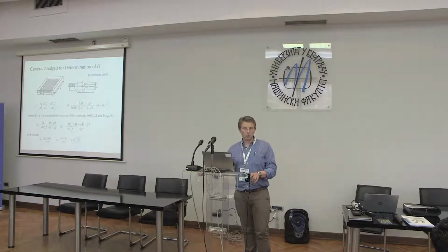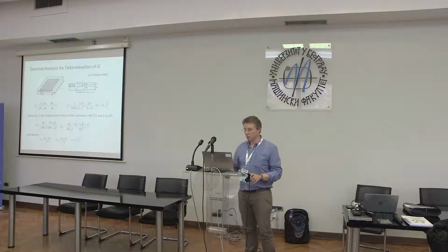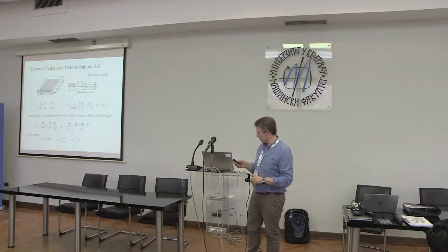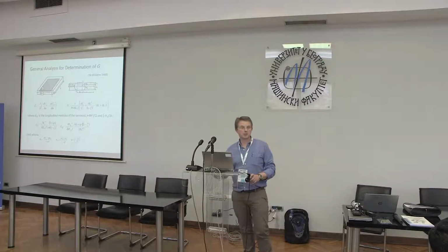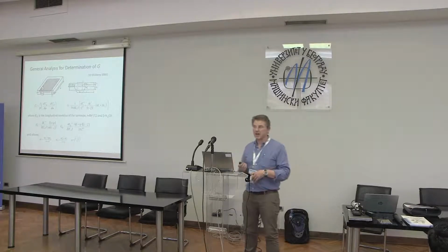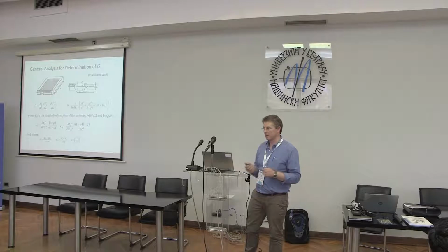Okay, so the important thing of this analysis is that it was a global analysis and worked on the basis of bending moments. So, for example, for any crack in the system, you would have applied moments M1 and M2 at one end, M1 at the other end, and just on the basis of those applied moments, you could determine what was happening with respect to the crack at the crack tip. So you determine energy release rates based upon global parameters.